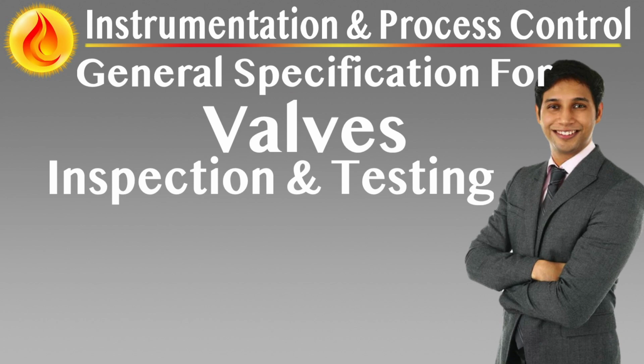Positive material identification, PMI, testing shall be performed for all critical pressure-retaining parts made of stainless steel, duplex, or CRA materials. Testing shall verify the chemical composition and ensure correct material selection per design requirements. PMI reports shall clearly indicate location, method, instrument calibration, and match valve body or part serial numbers. Supplier must submit a PMI inspection matrix covering all valves offered and confirm 100% coverage for sour service or critical isolation valves.